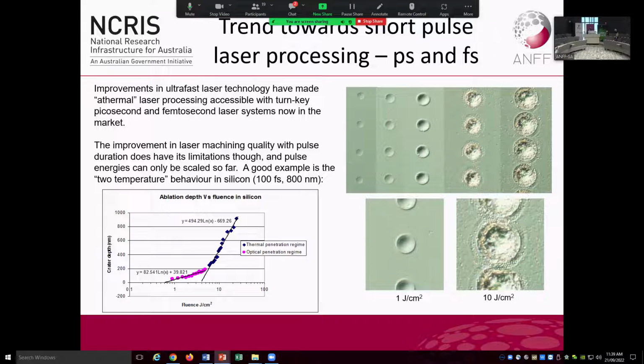For that reason, these ultra-fast processes are not necessarily super fast. Sometimes you have to be patient with your laser etching. One of the approaches these days is to scan the beam extremely quickly using galvanometers and things like that, and then use a lower energy but scan many, many dozens of times to get the feature that you want. That's where it differs from laser cutting. You saw at the start the laser cutting the steel, you just turn on the flame and away you go. These processes are more akin to milling or etching often.